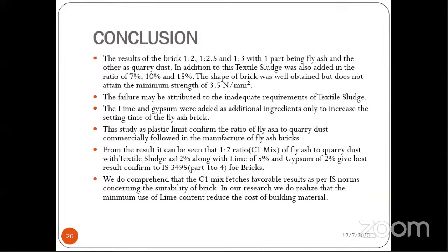And finally come to the conclusion. The result of the brick 1:2, 1:2.5, and 1:3, with one part being fly ash and the other quarry dust. In addition, textile sludge was added in the ratio of 7%, 10%, and 15%. The shape of the brick was well obtained, but it does not attain the minimum strength of 3.5 Newton per mm square as per IS. The failure may be attributed to the inadequate requirements of textile sludge.